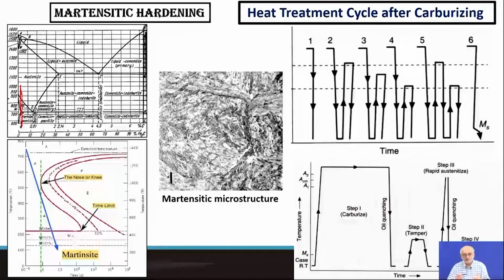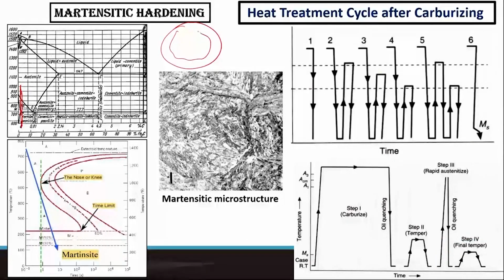So we require a core, and at least 90% of the component is soft. Initially we are starting with the entire 0.2% carbon steel, mild steel or low carbon, low alloy steel, and the composition is the same all throughout. Then we are just going to enrich only about 5 to 10% of the surface area with carbon and leave the remaining 90-95% unaffected, same composition. So the core, which is 90 to 95%, retains this low carbon region, whereas the surface or the case gets enriched to about 0.8, 0.9 or 1% carbon. So this becomes the surface. We create a differential composition across the thickness: surface enriched with carbon, core leaner in carbon. The objective is to create such a martensitic aggregate in the surface region.